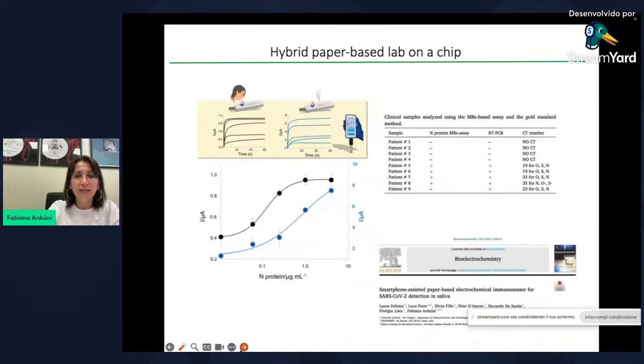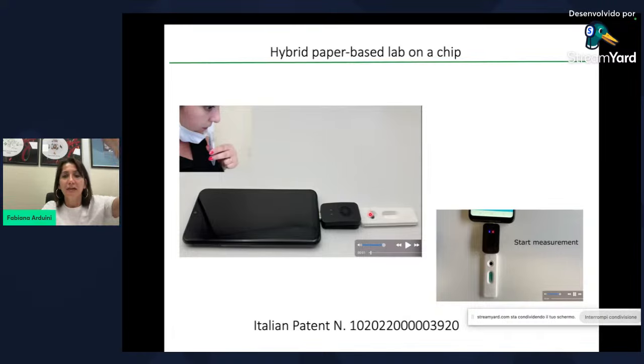In this case, this system works by adding one drop of the sample. We wait for it to happen in the solution, so there is the construction of the immunological chain. After, we add 2 drops to remove the unbound reagents, but now it's not needed to wash the solution, because the solution goes through the paper-based device. So in this case, the paper strip works as a passive pump, also as a waste reservoir. And after, we add 2 drops of the enzymatic substrate in order to have the reaction. In this case, we preloaded also a chloro compound that becomes light blue, indicating that everything works well.